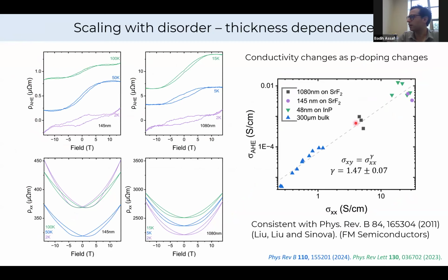So our samples are black and green, and then we overlaid some of the literature on bulk in this plot and some of the other films grown on indium phosphide. And then the data falls very well on this line, which on a log scale, this is a log scale and that's a log scale, gives us a scaling law that's a power law: sigma xy equal to sigma xx to the 1.5 almost.